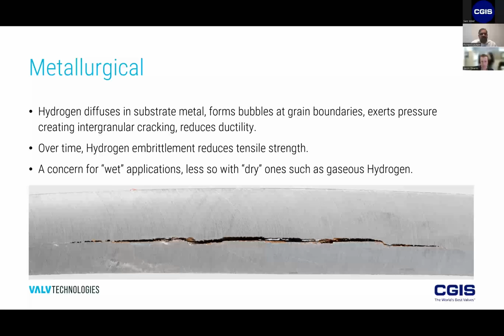If it's gaseous hydrogen, perhaps less so of a concern. But if it's what we call wet hydrogen, in other words, it's mixed with other impurities, then embrittlement can occur. And what we mean by embrittlement is the metal actually fatiguing or detaching, as the photograph shows. Really what happens here is that hydrogen diffuses into that substrate. It forms bubbles at the grain boundaries, and that pressure exerts into intergranular cracking. And ultimately, the material loses its ductility and its tensile strength over time. So embrittlement is a concern, which is why certain materials, such as the Belleville spring, have to use different types